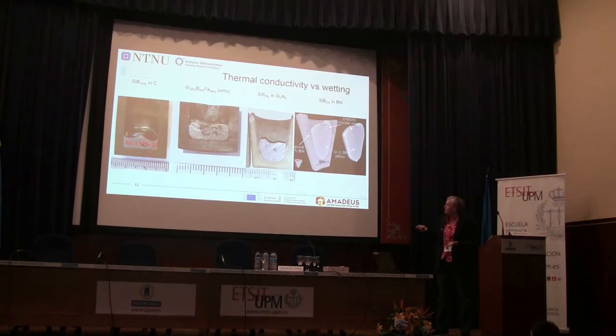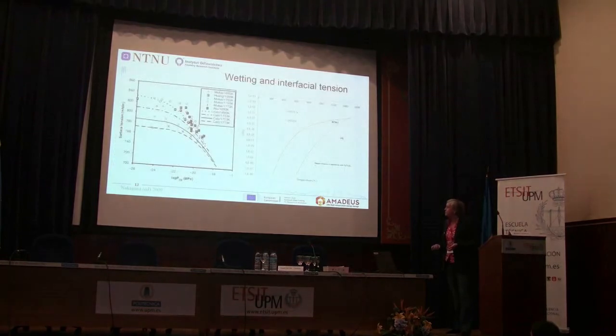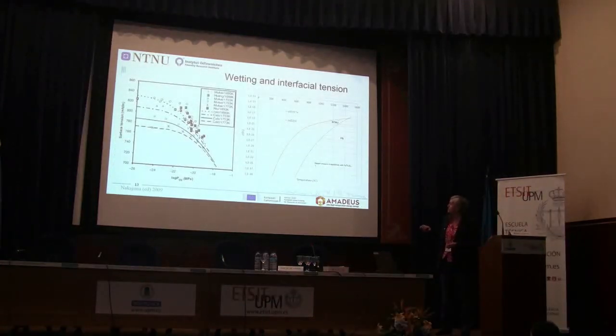If we look at what is affecting the wetting of silicon, one of the things that is affecting the wetting of pure silicon, this is data for pure silicon, is of course that the wetting is dependent on the interfacial tension. And the interfacial tension is dependent on the oxygen pressure in your system. We can see that this is very low. It goes from 10 to minus 18 to 10 to minus 26, so we are talking about really low oxygen pressures here. If we are in the high oxygen area, we get a different surface tension. It goes from around 700 to about 840 at 10 to minus 26. So the surface tension between liquid and gas will be affected.